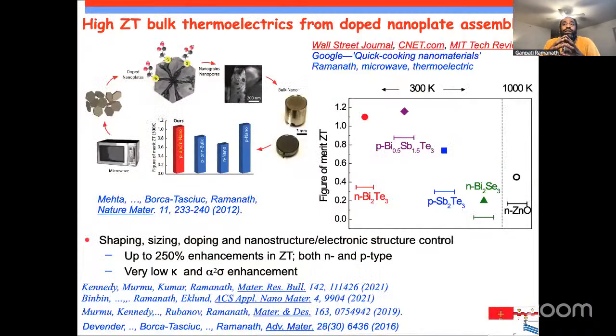What we did then was we did this for a whole lot of materials where we were able to shape and size the nanostructures. In this particular case, we were able to make nanoplatelets. And we were able to do this by a scalable microwave process where chemistry does the job for you. So we just put in the right reagents, the right surfactants, and then microwave it. You just cook it, just like heating or cooking something in a microwave. And we get these platelets decorated by these molecules.